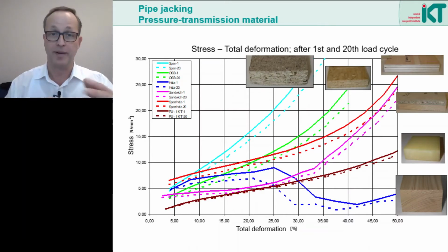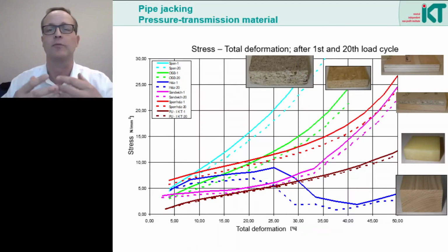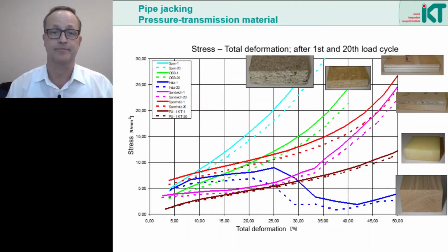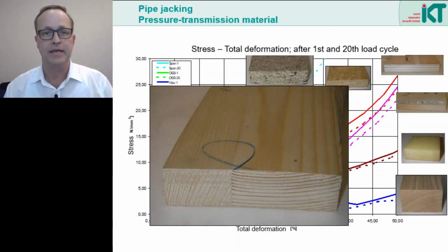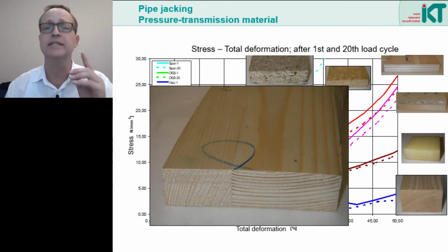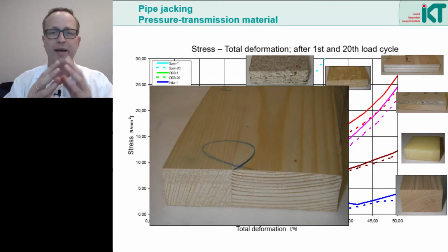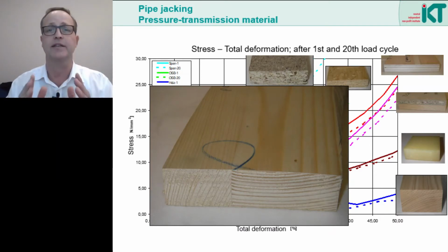Then below, the plastic block with the brown line is relatively soft but shows almost no plastic behavior. It is largely elastic. And the lower dark blue line shows the behavior of the solid wood sample that breaks at a critical stress and then no longer shows any significant load-bearing behavior. And with solid wood, please keep also in mind the fiber orientation really makes a difference.